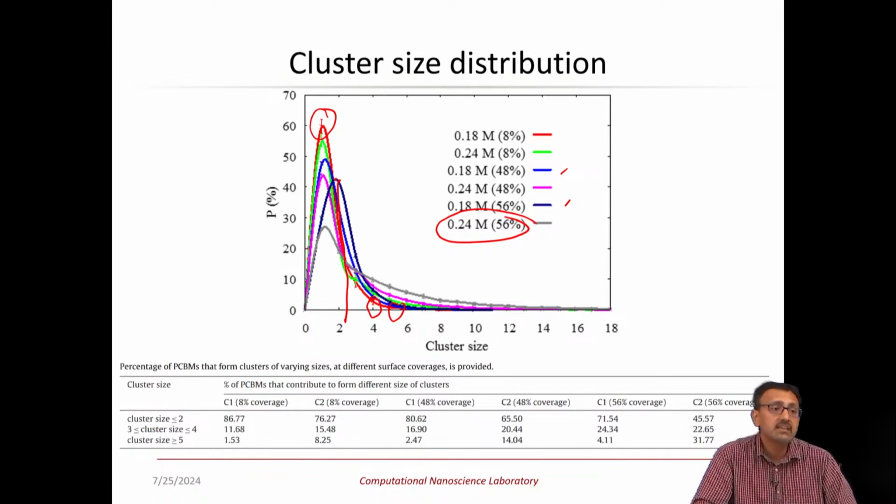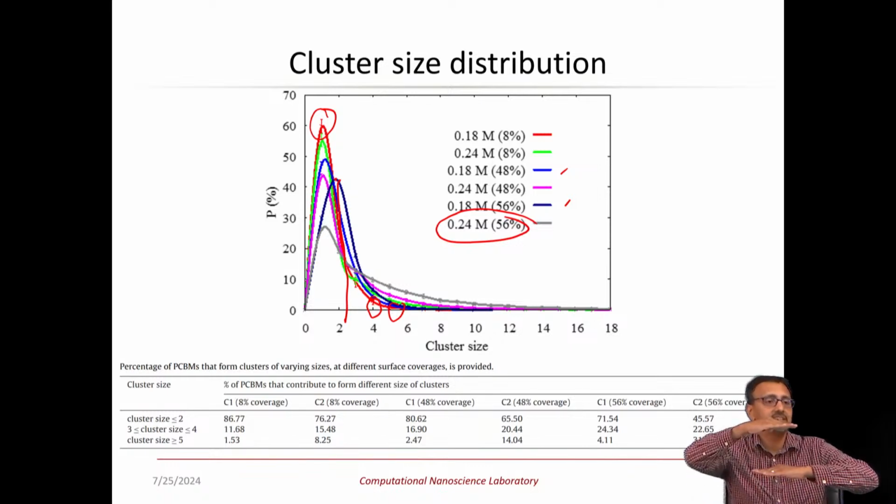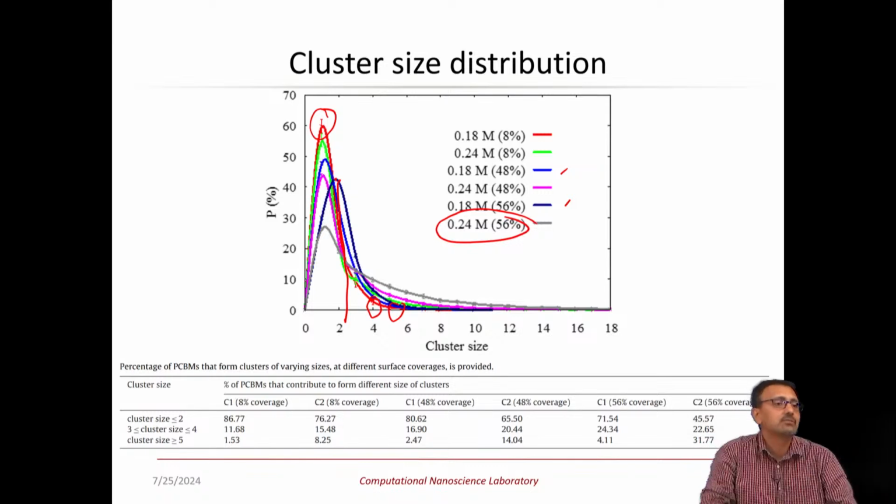NPT, or let's say NVT. I believe in this case we looked at NVT, the canonical, because we had two substrates and we didn't want oscillations of the surface. So, we maintained a constant fixed volume which was carefully equilibrated. So, what is the challenge with that?